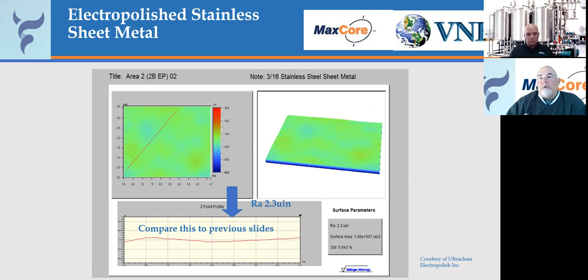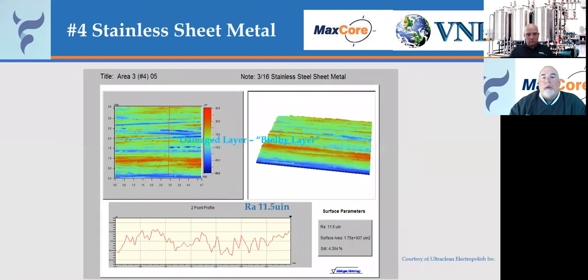So let's go back for just 1 second when we're talking about electropolishing. What do we do? So electropolishing is really nothing more but a controlled corrosion process. Okay? You basically have your vessel that is becoming the anode. Your electropolishing tool is basically your cathode. Your electrolyte is your electrolyte on the surface of the steel.